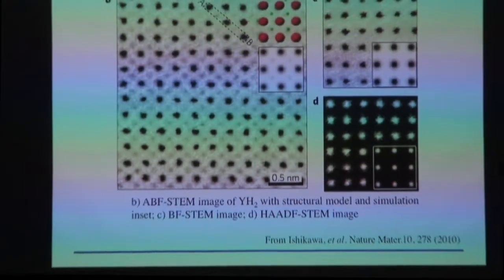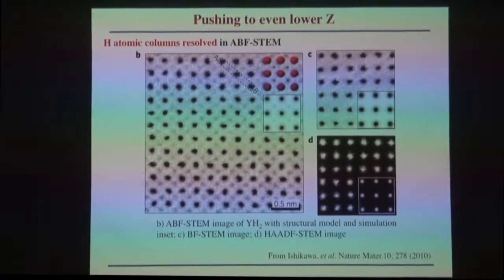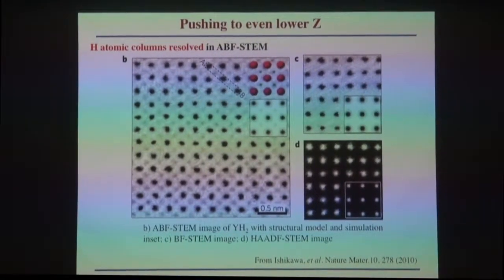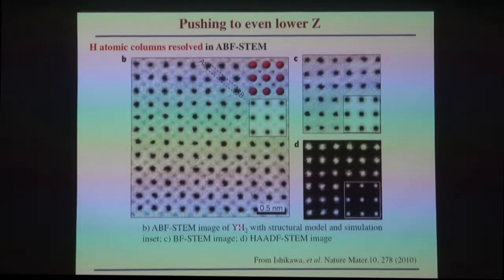Okay, yes, sir. You mentioned that we can see the hydrogen column using STEM. But is it possible to see the segregation of hydrogen, for example, at grain boundaries using TEM or STEM? I think you're not going to see individual hydrogen atoms in the electron microscope. But how about segregation? And how would you see segregation unless they are well aligned? I mean, this is a quite thick sample of yttrium hydride. This is not just single atoms. It is a crystalline material, and the atoms are very nicely located and held in particular places. I mean, there is the projected crystal structure.